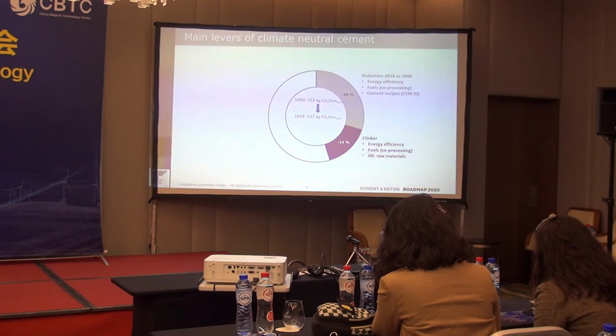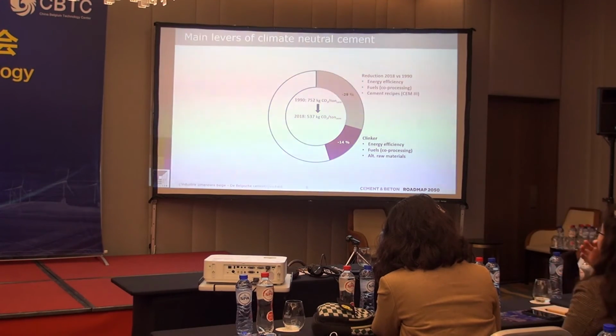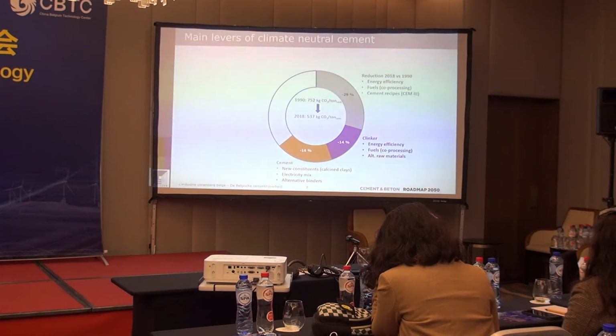Some waste from deconstruction can be reused in the cement kiln because it has already been decarbonated, and so it reduces the amount of CO2 which is emitted during the production of clinker. Further, we will work on the cement part of it and the recipes, new constituents that can be used for cement production, and one of particular attention is what we call the calcined clays. There is a famous project called LC3, from the University of Lausanne, and this goes in the right direction.